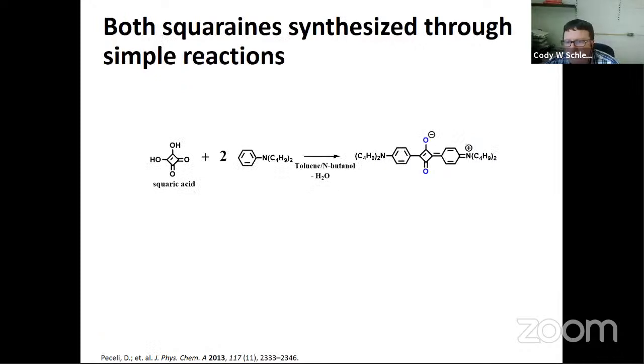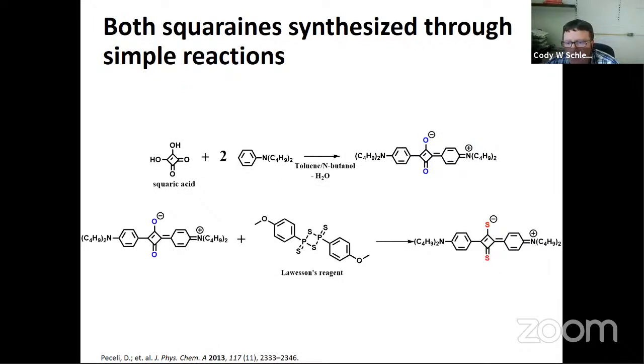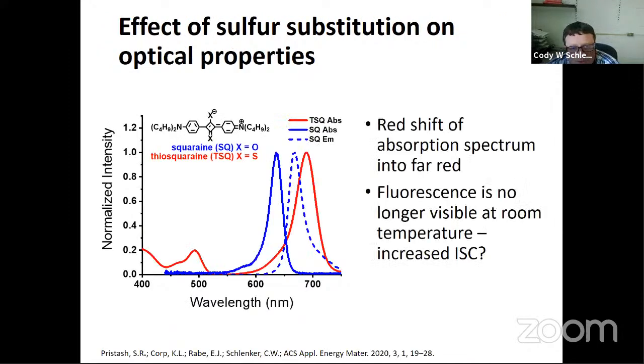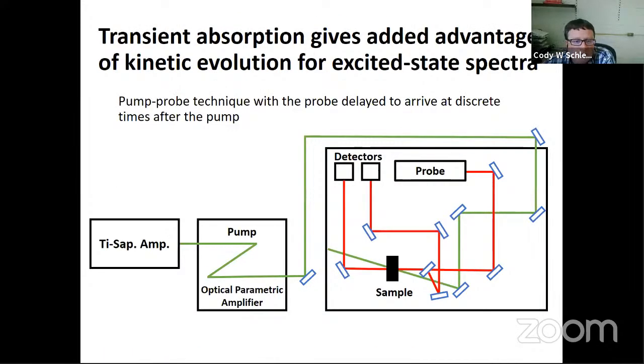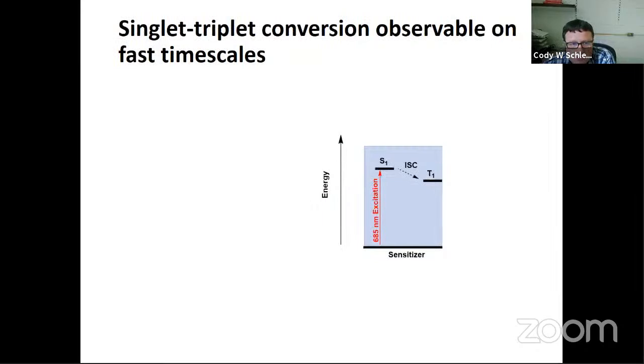Okay, so we make some molecules, we make these squaraine molecules. It's pretty much a quick reaction where you've got a condensation reaction of a squaric acid, and in our case, we've got an aniline donor unit, and then we thionate it with Lawesson's reagent. And so you can see the absorption here. It shuts off the fluorescence when you thionate and introduces some process for spin orbit coupling. We use transient absorption to monitor the excited state kinetics for these things, so we can watch the intersystem crossing process.